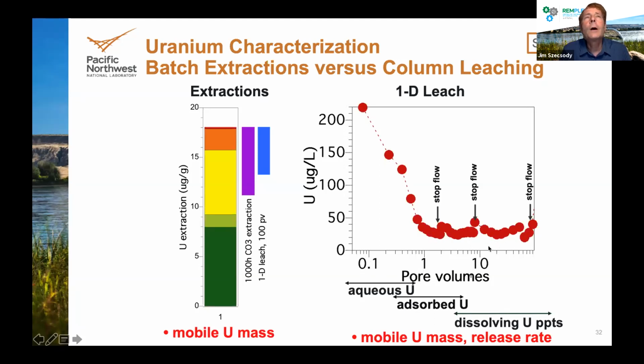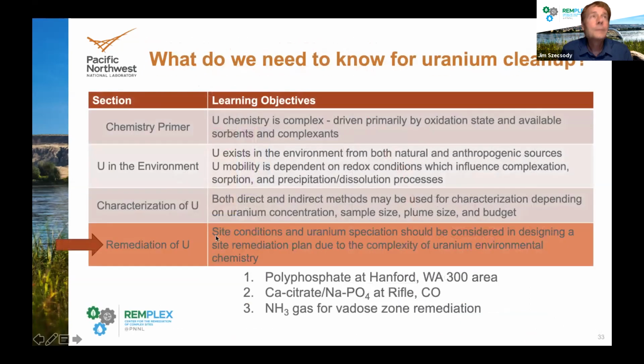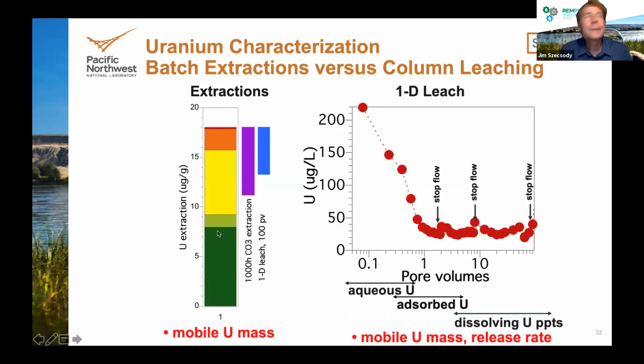And we can integrate all the uranium we got out under that, so we can get a total mobile mass. And if we simulate this experiment, we can also get a uranium release rate. Now that total mass that we got from that experiment, I've plotted on this left side in this blue bar. And so we can compare it to the extractions, which on that same sediment, we have aqueous adsorbed, high solubility phases, low solubility phases. And you can see that aqueous and adsorbed uranium leached out, and some of these high solubility phases dissolved too and then leached out, but these ones do not.